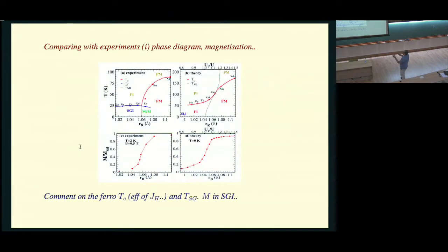So firstly, a comparison with experiments. This is a bit of a show-off. So if you calibrate your parameters in the light of what density functional theory tells you and compare transition temperatures and magnetic moments, notice there is a factor of 2 here. Modulo the factor of 2, which I'll justify in a moment, you see that the character of these curves, this versus this, is not terribly different. I don't get a spin glass because of the absence of disorder. The magnetic moment in the ground state, if I'm in the metallic phase, I get a large moment. As I go through the transition into the insulating phase, I get a small but still finite moment. Doesn't do too badly between theory and experiment.